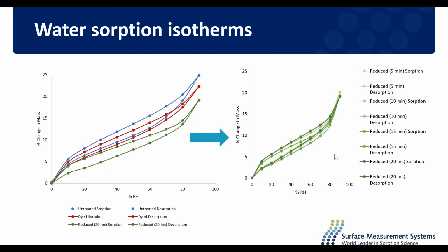And now here's just showing all the reduced samples together. And as you can see, they all look fairly similar. And again, that's quite interesting because we went from a 5-minute reduction all the way to a 20-hour reduction. So there's a great spread of crosslink density here, but they are all relatively similar. And again, that sort of highlights the point that perhaps that introduced hydrophobicity from the methylation procedure is the most important factor here for the water sorption property.